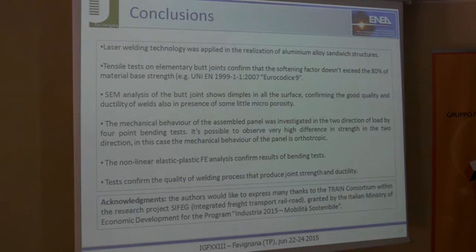In conclusion, laser welding technology was applied in the realization of aluminum sandwich structures. Tensile tests on the elementary butt joints confirmed that the softening factor doesn't exceed 80% of the base material strength, like Eurocode 9. And the mechanical behavior of the assembled panels was investigated in 2 directions of load, and in this case the mechanical behavior of the panel is orthotropic, and the nonlinear elastic-plastic finite element analysis confirms the results of the bending tests.